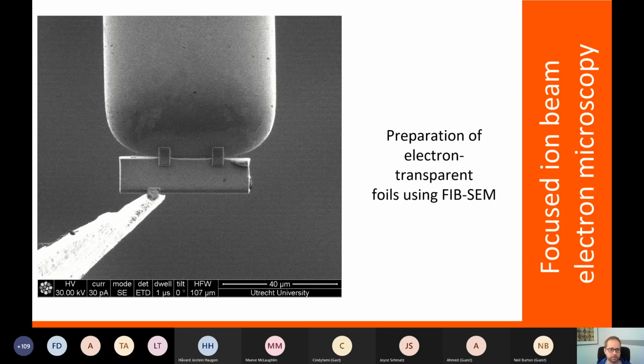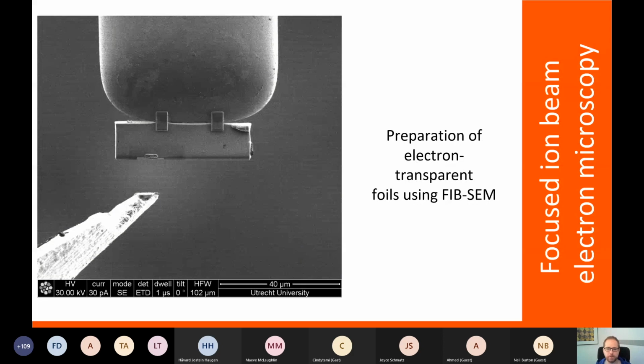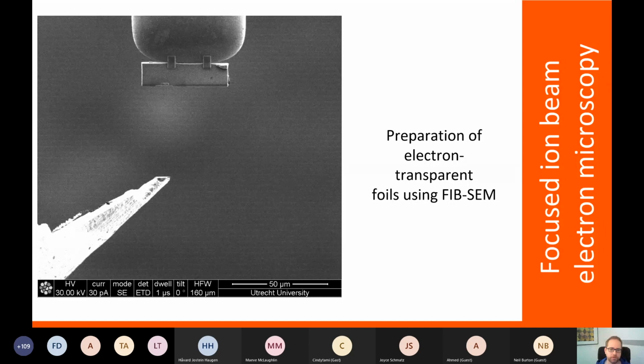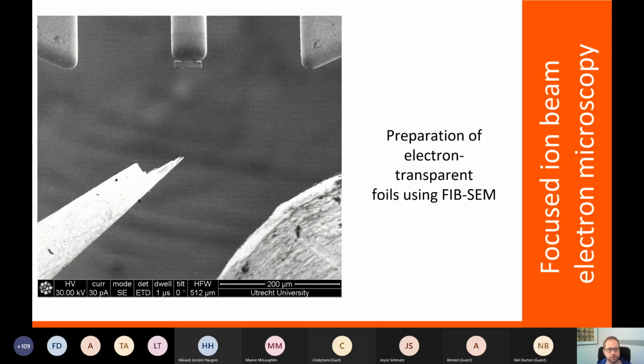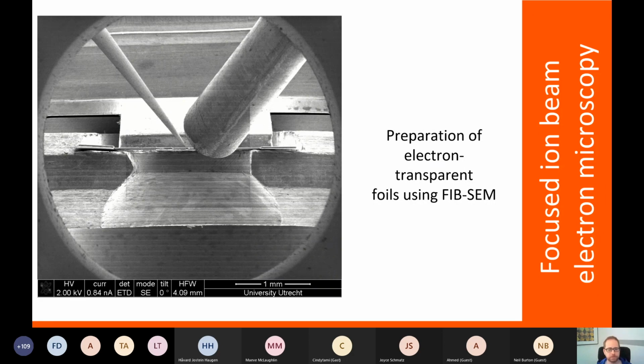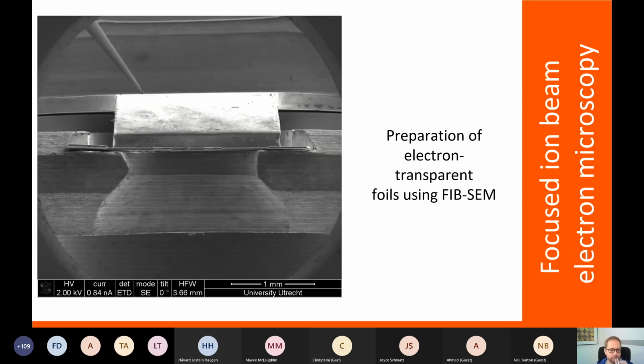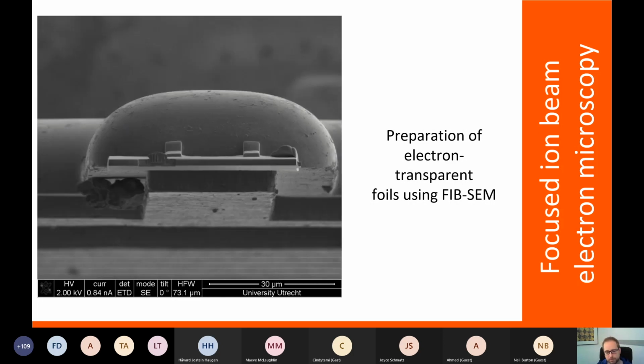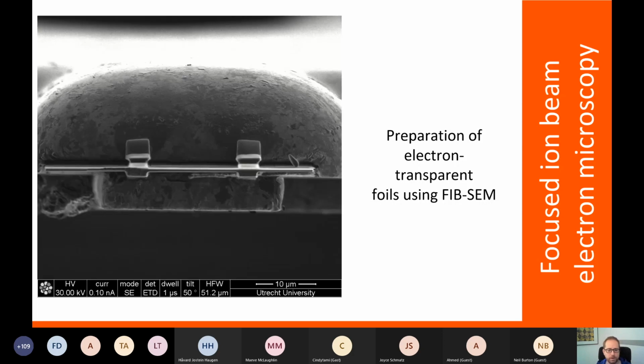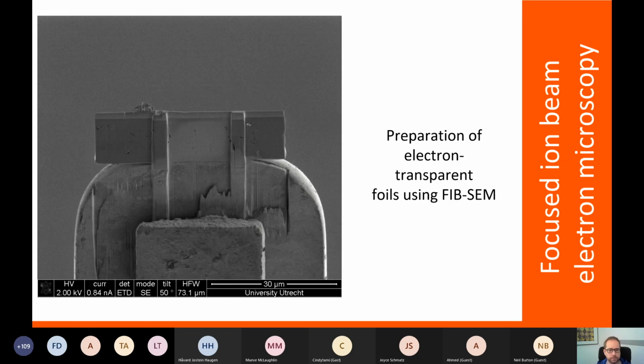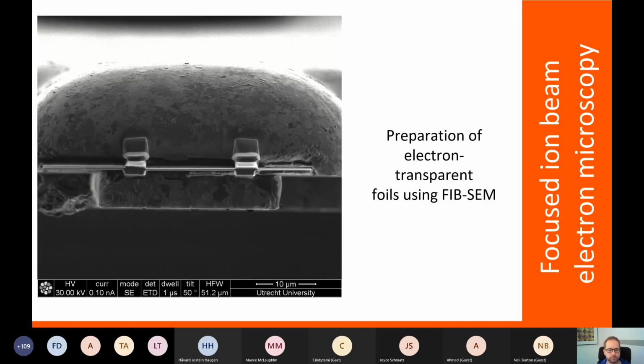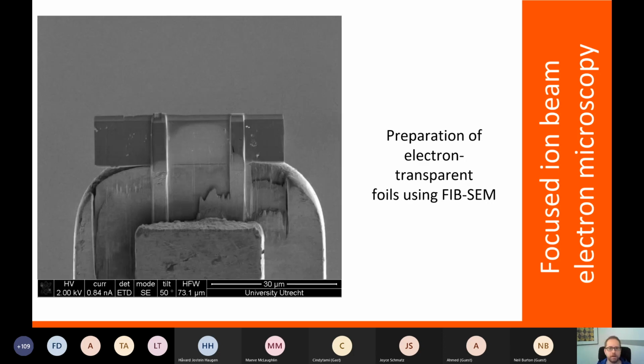Then we cut off the needle. And now we have this tiny sample across an interface, through porosity, across a grain boundary. There's an infinite amount of options. We will take away the gas injection system and the needle. And now again, we use the gallium ion beam to make this sample extremely thin, typically on the order of 100 nanometers. So you see the sample is still relatively thick, 1 to 2 micrometers. And now we will thin it down until it is very thin, 100 nanometers about. Then it becomes electron transparent, and we can now take this sample with this holder and transfer it to a transmission electron microscope.